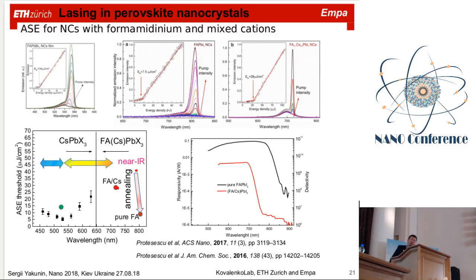And what we also observed for such material, due to this merging of nanocrystals, is that we start to observe electrical transport in such material, which we show in photoconductivity effects. So this material would also work as a photodetector, which is very important. I will show you a couple of slides later.